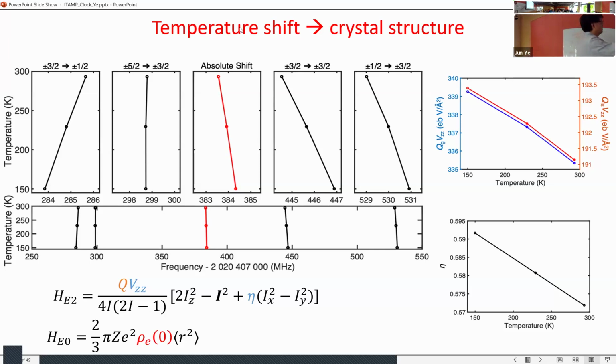This is the so-called absolute shift. This red line still moves. That's because the electron charge density around the nucleus is changing, and you can determine that quantity as well. The point I want to make is that clock makers and metrologists will look at this line, saying, well, it's not really straight. There must be temperature dependence, and that's true.